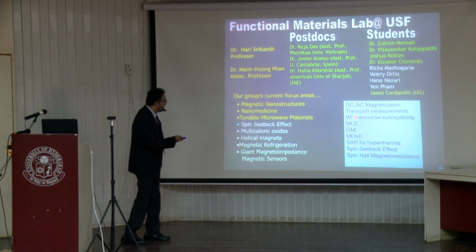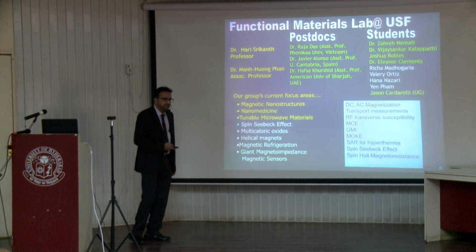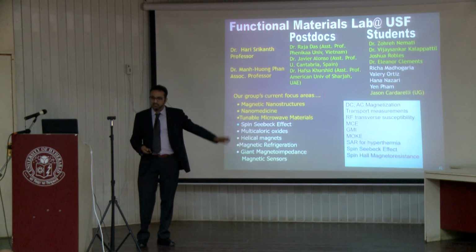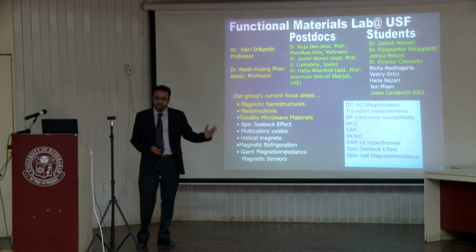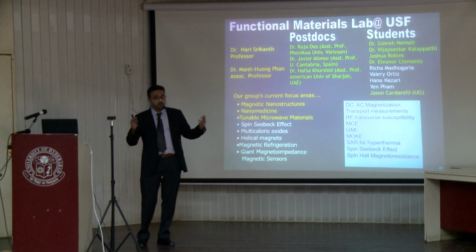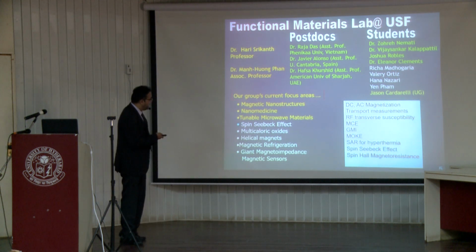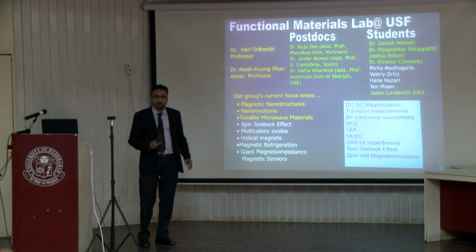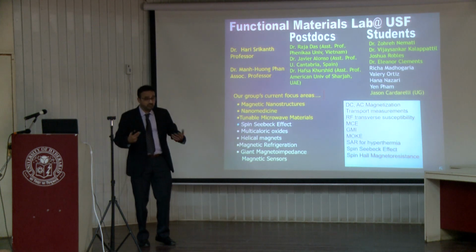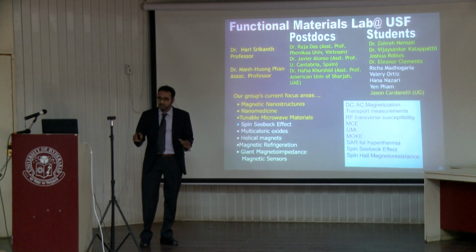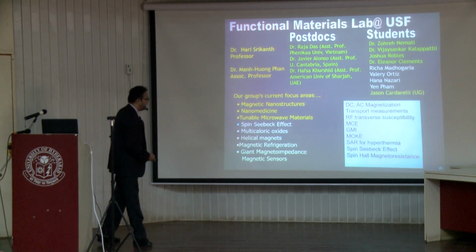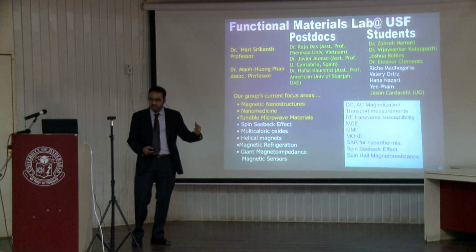Okay, so the other thing that I want to mention is this unique method, radio frequency transverse susceptibility. It's somewhat similar to FMR, and I know that Hyderabad has been very well known in the field of ferromagnetic resonance for many years in magnetic materials. Professor Kaul is a household name in magnetism here. And basically what we do is something very similar, but with this technique, it's done at radio frequency, high frequency. We have very good sensitivity, and we can measure the effective magnetic anisotropy, as well as switching fields, which are the most fundamental parameters that you want to know in magnetic materials. Okay, and this is going to play a key role in today's topic, because I'm going to focus on anisotropic nanoparticles.